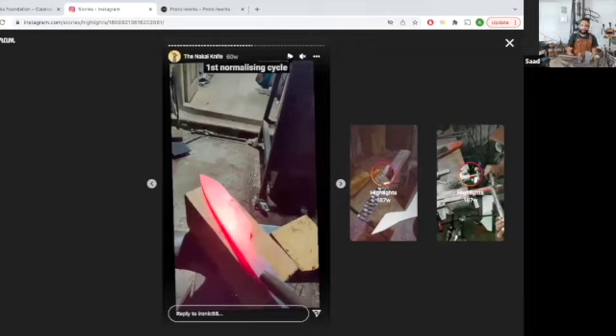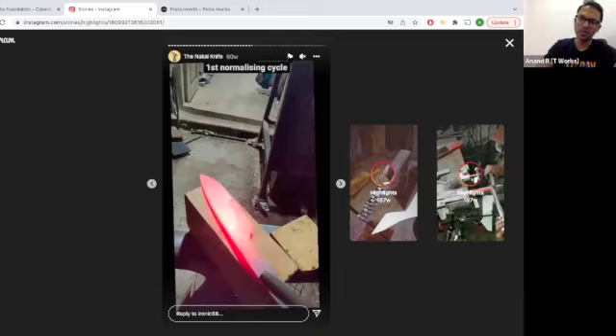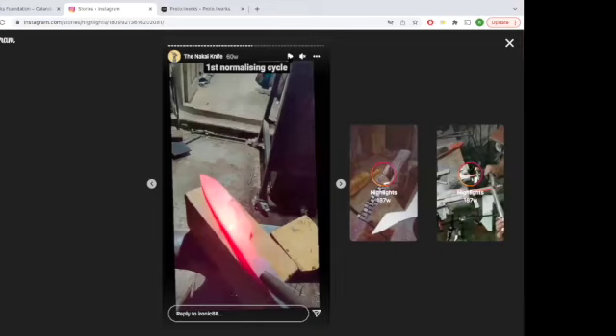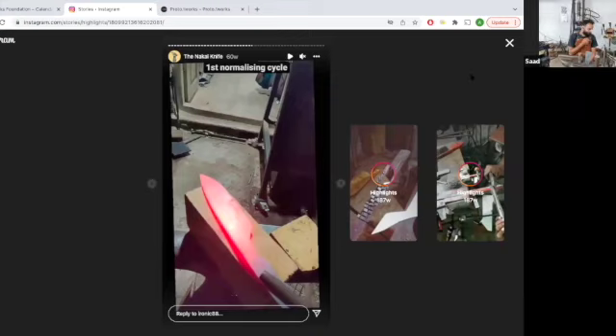So yeah. Now after hand sanding, this is me normalizing the blade. Normalizing is where you bring it up to critical temperature and you let it cool down in air. What is critical temperature? Critical temperature is where, I don't remember the technical terms, but the steel grain structure starts changing. So what happens when you're forging, right? Because you're doing such violent processes to forge the steel out into a knife, there's a lot of stress that's developed within the blade. So after you're done with shaping, hand sanding and everything, you put it in the forge, you bring it up to critical temperature and you normalize it.